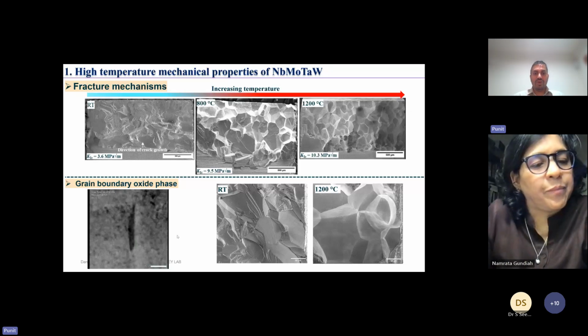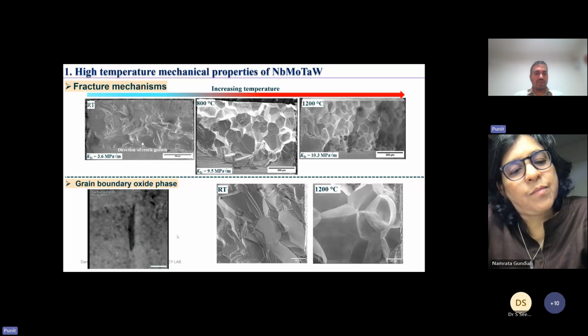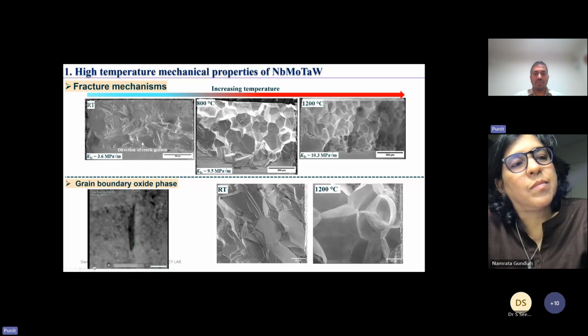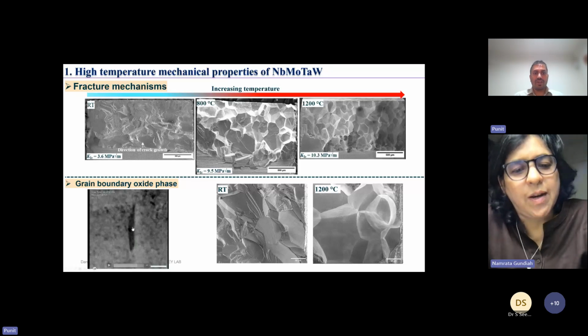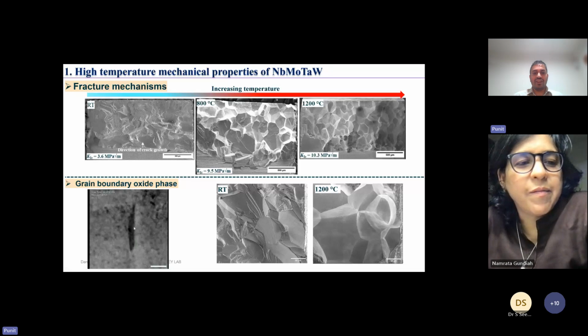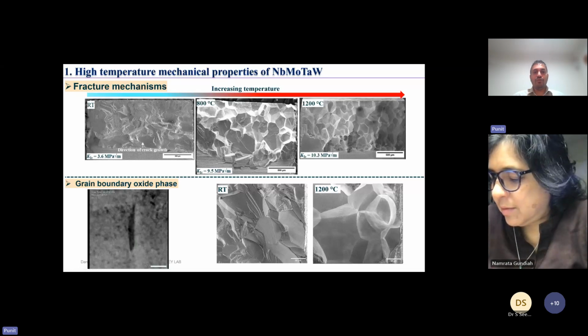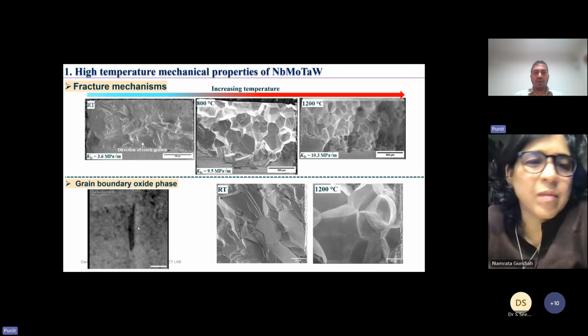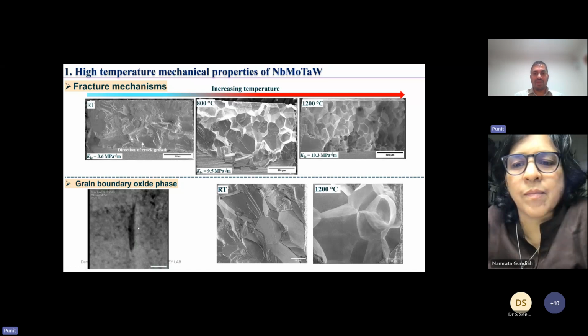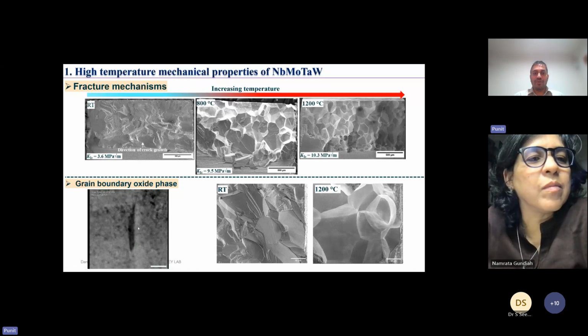In TEM, because you have a high vacuum and you are using high electron volt electrons, you degas the oxygen from the oxide particles around 850 or 900 degrees, when the polymorphic change happens. But when you are not applying any stresses inside the material, the oxygen is not actually going out from this oxide phase. Their structure changes. We don't have any verification of that, but that's our theory: the structure changes, but when you cool down, the structure reforms. Understood.